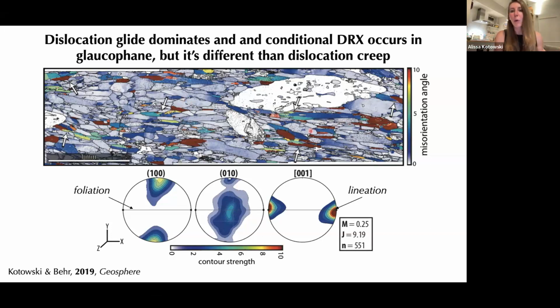We see big porphyroblasts here with zones of relatively high misorientation at their margins. And we see small little grains with relatively no internal misorientation. We also see a really, really strong crystallographic preferred orientation, the strongest one that we've seen in the samples that I've shown you. So all of this microstructural evidence is nominally consistent also with deformation and dynamic recrystallization accommodated by